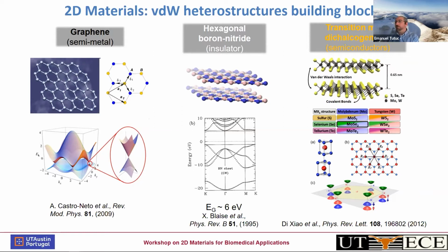Now, a close material that has a similar lattice as graphene is hexagonal boron nitride, with the difference that one atom of carbon is substituted with nitrogen, the other one with boron. A sublattice asymmetry in graphene opens a gap. This is one structural way to introduce a sublattice asymmetry, by substituting one site with one atom, boron, the other one with nitrogen. And this turns it from a semi-metal into a high gap semiconductor. It has a band gap of 6 electron volts. It can be considered a semiconductor, but for practical purposes, hexagonal boron nitride in van der Waals heterostructures is a supporting actor. It's a dielectric, and occasionally a tunnel barrier.